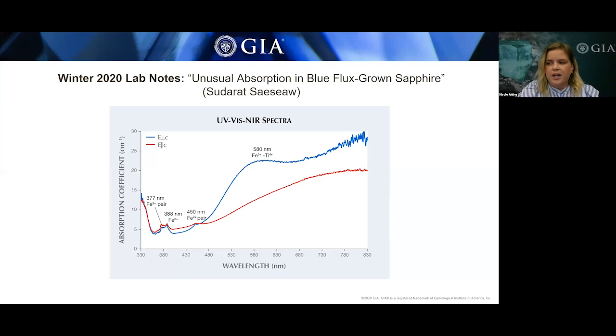But additionally featured is an unexpected broad band around 800 nanometers. This band is typical for basalt-related natural blue sapphires and can be found in some heated metamorphic blue sapphires as well. However, it has not been reported in a blue lab-grown sapphire, either flame fusion or flux grown.